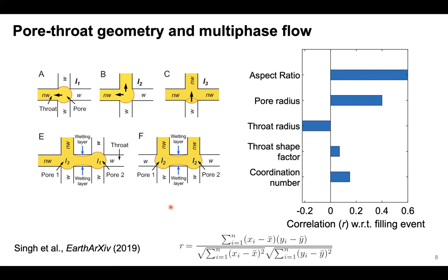So this analysis, maybe in the future, we can use in pore network models to improve them. But again, some more work is needed and also more experiments are needed to generalize this aspect. The minimum aspect ratio we found from these experiments is slightly more than 2, which is consistent with the theoretical values, but is slightly more than what people have found on 2D micro models. So maybe the differences are the nature of 2D and 3D there.